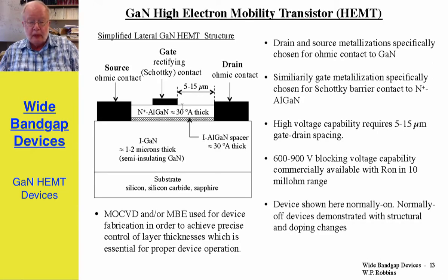N-type aluminum gallium nitride. And then windows are opened up for the source and drain contacts, which are ohmic contacts, and then also a rectifying contact, a Schottky barrier contact, for the gate. The drain and source metallizations have to be specially picked to get the ohmic contact, and similarly for the gate metallization. High voltage capability requires that the distance between the gate and drain be 5 to about 15 microns.